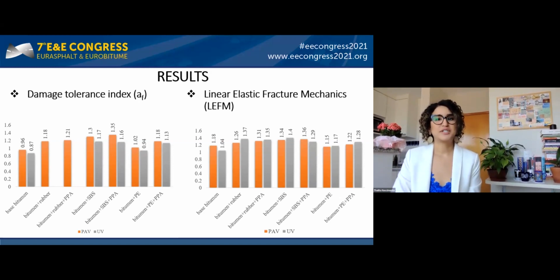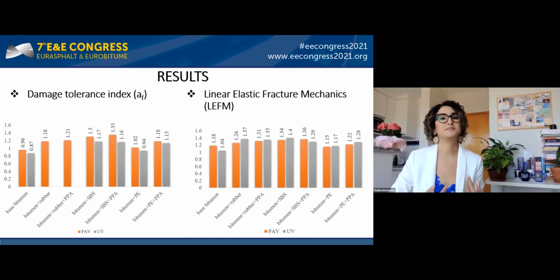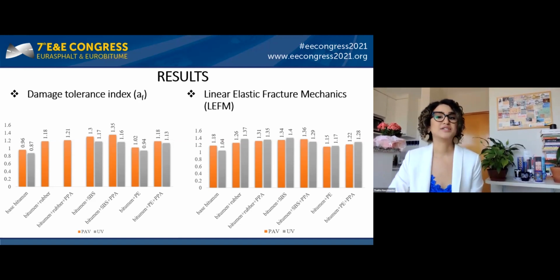However, when the analyses were obtained by the LEFM approach, it was the opposite. Most materials present crack length at failure higher on the UV aging condition. And for both methods analyzed, we can see that the use of modifiers increased the fatigue resistance.